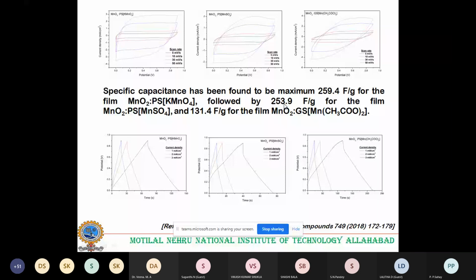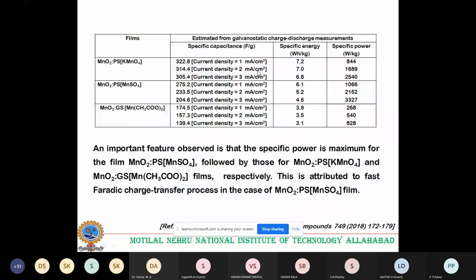So this is from the cyclic voltammetry. We calculated the specific capacitance from the galvanostatic charge discharge measurement, and there you will see that in case of the KMnO4, these are the specific capacitance values for 1, 2, 3, and for the MnSO4, when you prepare the film with the MnSO4, this is the value. This is the value calculated from galvanostatic charge discharge measurement, and this is your specific power. If you look at this one, the specific power is more here in this case compared to the previous one. So this is the important feature.